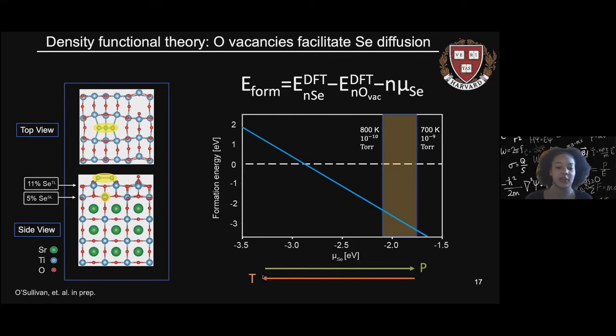And based on these, our experimental conditions are approximately in the orange region, where we have realistic experimental conditions. This is along the axis of selenium's chemical potential. We then calculate whether this configuration is energetically favorable, and we find when we take into account the energies of the relaxed structure atoms and the chemical potentials of selenium, we can plot the formation energy as a function of this chemical potential corresponding to experimental parameters.